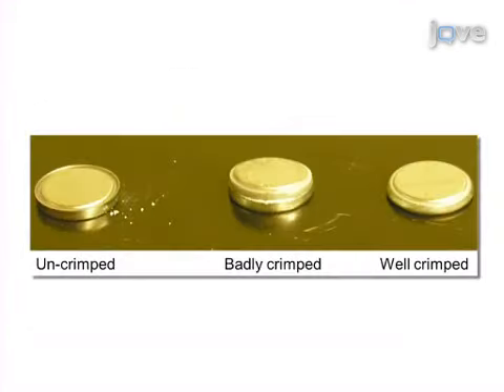After the cells are assembled, they are crimped to obtain a tight seal to protect from moisture. Typically, a badly crimped coin cell splits open after a few hours in ambient temperature due to the swelling of the lithium foil after reaction with moisture.